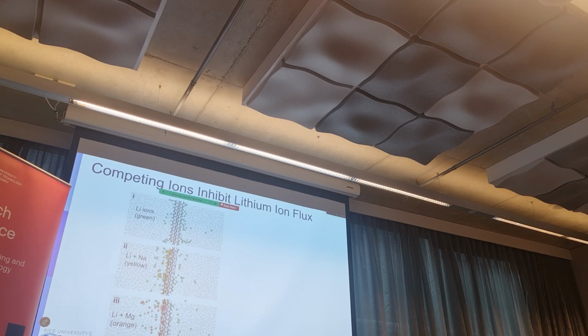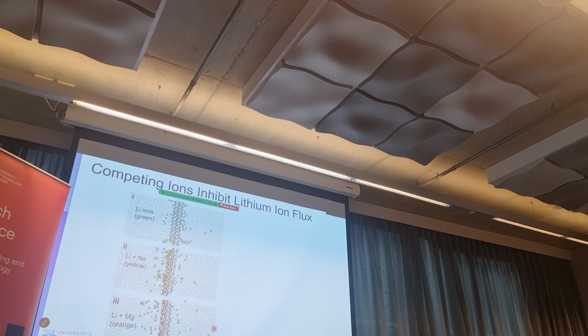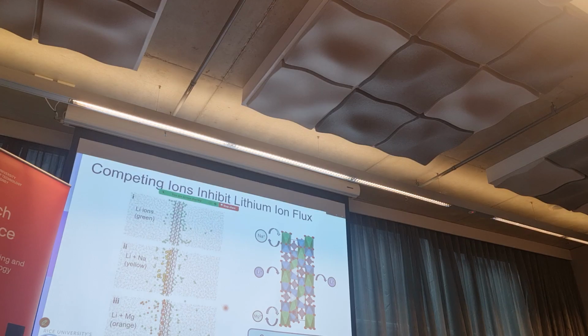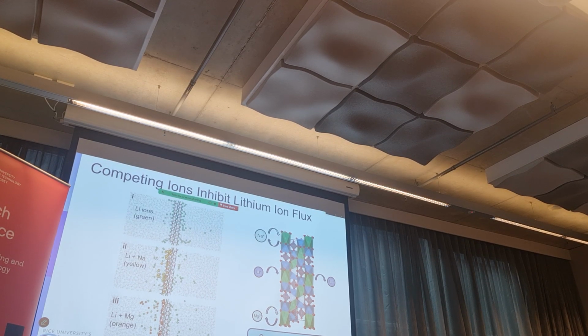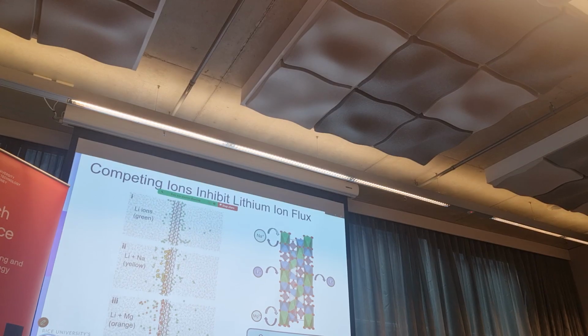Magnesium, the orange, gets only to the first layer and cannot move farther—only the lithium goes through. This is a phenomenon we need to overcome. Competing ions do not penetrate past the surface, and they interfere with the partitioning and further transport of the lithium ions.